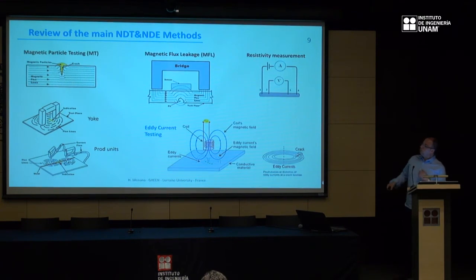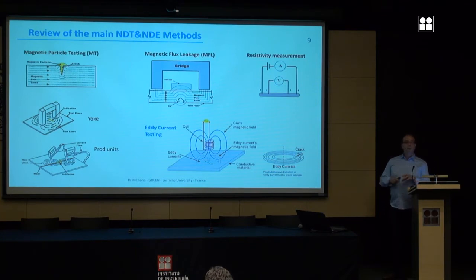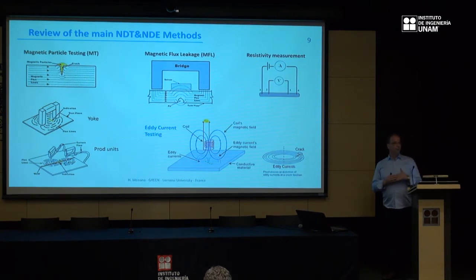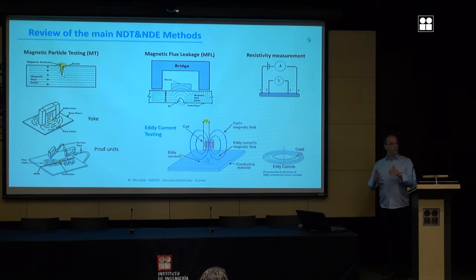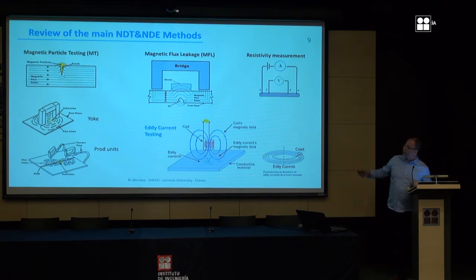Move forward. I put here all the magnetic and electromagnetic testing methods. I begin by magnetic particle testing, on the left. Here, when it concerns cracks on magnetic materials, we spread a liquid loaded with magnetic particles on the surface of the material, and then we apply an external magnetic field. The magnetic particles will fill the cracks to reduce the reluctance of the material. So you can get a map on the surface of the tested material formed by the magnetic particles, which